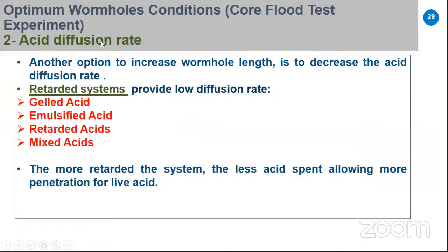The second parameter that makes our optimum wormhole is the acid diffusion rate. As you decrease the acid diffusion rate, you get an increase in wormhole length. Usually we reduce acid diffusion by using what are called retarded acids. This includes gelling acid, to make them high viscosity with polymer or surfactant. Then we have emulsified acid, where we increase the viscosity by adding diesel to the acid. We also have retarded acid like alkyl sulfonate or alkyl amines. These retarders are added to the acid to slow the reaction rate. And also we have a mixed acid between organic acid and HCl. So the more retarded the system, the less acid is spent and the acid will be live, so we have deep penetration for live acid.